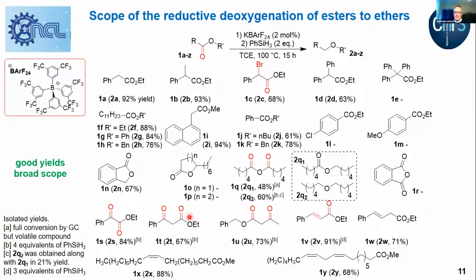Other derivatives like this, two other esters substituted by carbonyl in two or three positions, were also reduced effectively, including these conjugated esters. We could reduce at the same time the carbon-carbon double bond and the carbon-oxygen bonds. However, once the carbon-carbon double bond is no longer conjugated with the esters, we have no reduction of it.